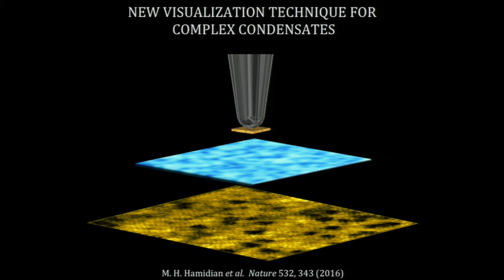Yeah, you can't scan over that part again. As soon as you, as an STM operator, sit there and look at your screen and there's a change, you stop everything. You pull the tip back, and then you move far away, and you land. And that topograph that I showed you, which looked perfectly periodic, was a really telltale sign that you had picked up one of these really nice flakes. So I'd say the success rate once you did the proper field emission on gold is somewhere between 10 to 20%. It's not bad.